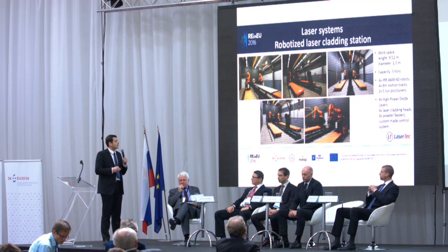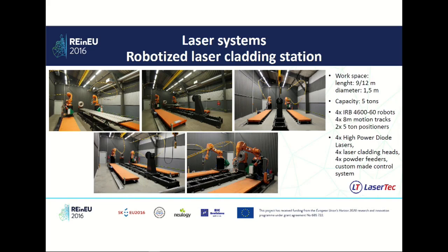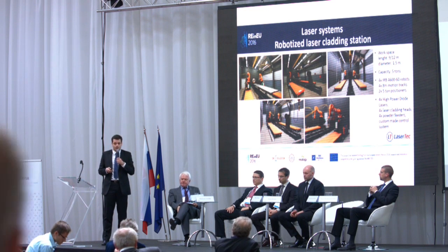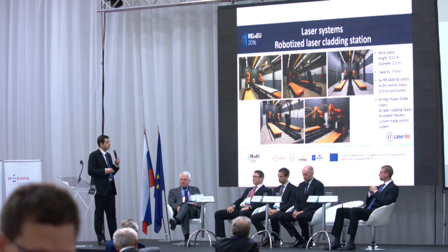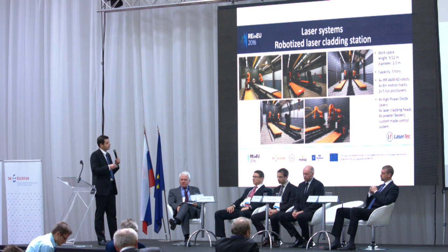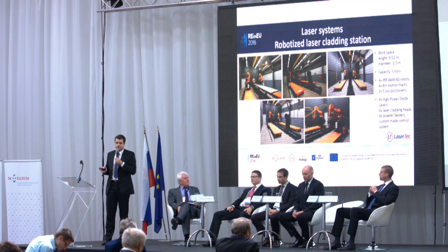Example of a cladding application. This station was delivered also to a Polish company which clads corrosion and erosion resisting coatings for the energy sector. At the moment they are using it to clad Inconel base alloys on steam boiler walls. As you can see, 4 robots with 4 motion tracks. This is just a picture of one of the stations. They have 2 of these, 4 lasers and a custom-made control system for the whole station. The advantage of using laser technology in this case was that it is possible to clad very thin coatings, 0.5, 0.6 millimeters instead of cladding 3 millimeters using arc technology, which is the standard.